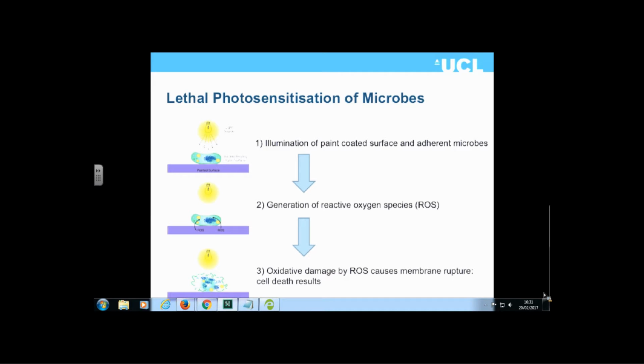It can be titanium dioxide, or it could be a dye or photosensitizer dye. When we've done that on our painted surfaces, we found that bacteria find it difficult to stick to the surface, and we can generate reactive oxygen species when we expose them to light, even just very weak light, like what you'd get in an indoor environment.